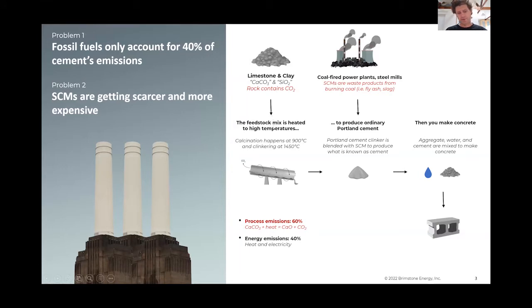Grind it into a powder and put it into a kiln, and typically with a pre-calciner. And in that kiln, you first get a heating step up to 900 degrees Celsius. And at that step, this reaction in red occurs, where the limestone decomposes into lime, which is calcium oxide, and CO2. So this chemical reaction here is why cement is considered difficult to decarbonize.